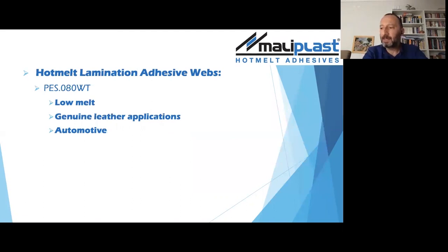And the last product in the hot melt adhesive web part is the 080 WT, which is again a low melt hot melt adhesive web. It has got around 70, 75 degrees melting range, which is very good for any kind of material which is heat sensitive. It can be membranes, it can be genuine leather, or it can be synthetic leather, where the surface or even the material itself can be sensitive to the heat stress which can come from the machine during the lamination process.